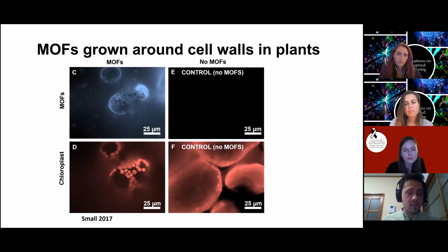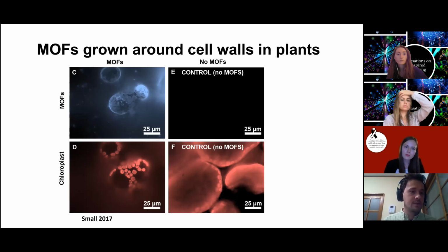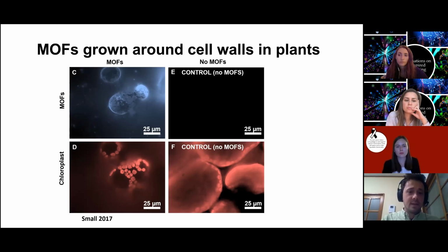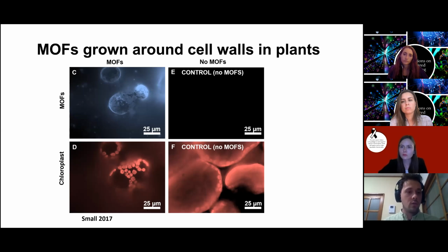And if we grow our MOFs around these cell walls, which is the left-hand column, we can see that we have beautiful MOFs all around it. Of course, if we don't grow the MOFs, if we just put one of the precursors in, for example, just zinc or just 2-methylimidazole, we don't see any of the fluorescence that we would get from this MOF. We see that the coating around in that C panel is quite strong. It looks fairly uniform. There's some blotchiness, but for Z sections, it turns out that's more of a focal issue. And if you look really hard, you can see that actually the chloroplasts are coated too. We can see these from electron microscopy images. So this was our first evidence that we truly could coat more complex living things.